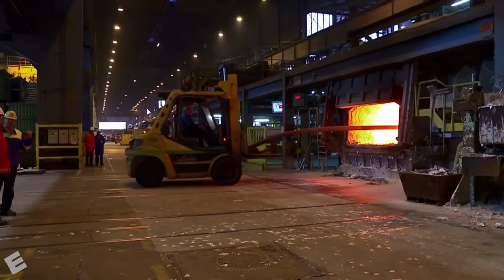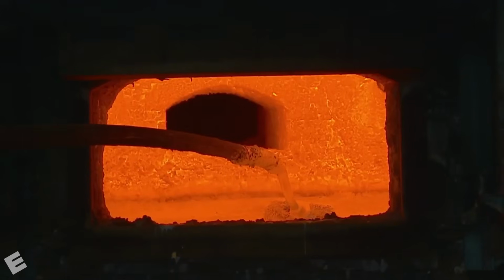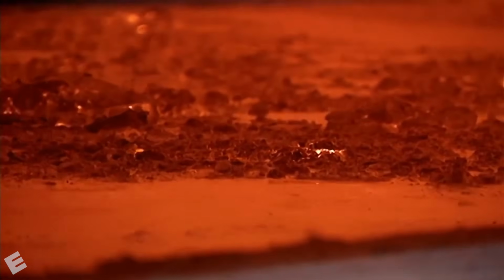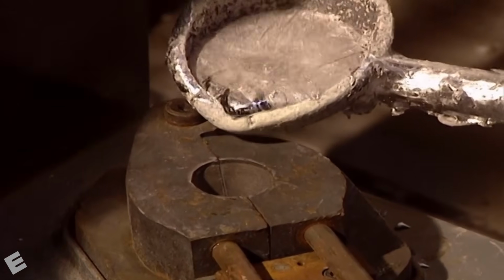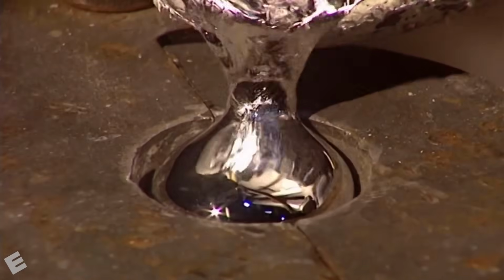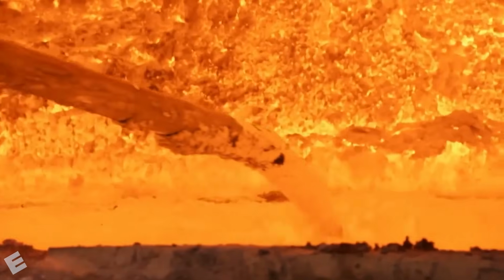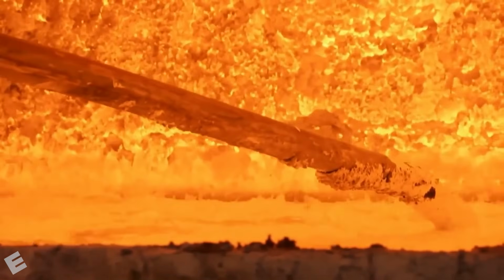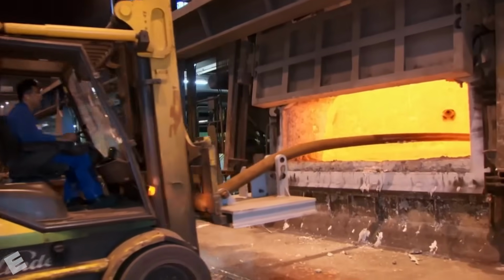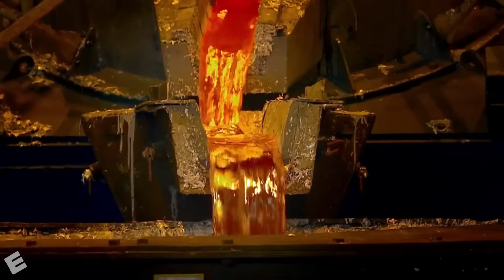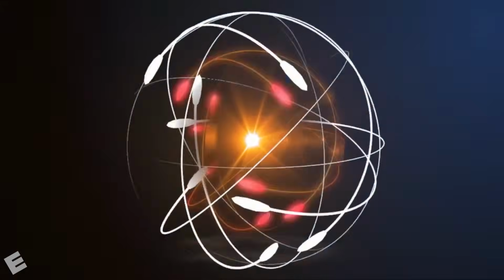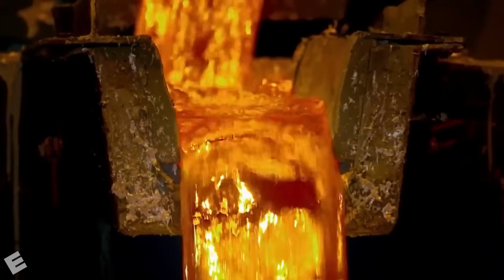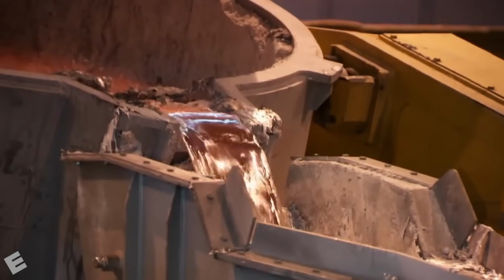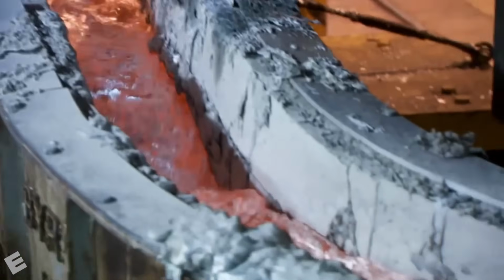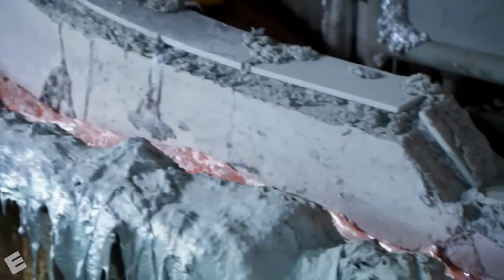Inside each pot, alumina is dissolved in a molten mineral bath at about 1,740 degrees Fahrenheit. Well above aluminium's melting point, a powerful electric current passes through the mixture. The electricity breaks the chemical bonds connecting aluminium and oxygen. The oxygen reacts with carbon near the top of the pot, while the denser molten aluminium collects at the bottom. Producing primary aluminium requires enormous amounts of power, several times more than producing the same amount of steel. Electricity alone can represent a major portion of the total production cost.